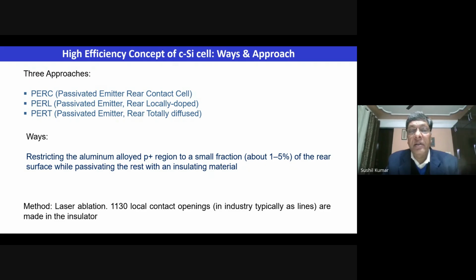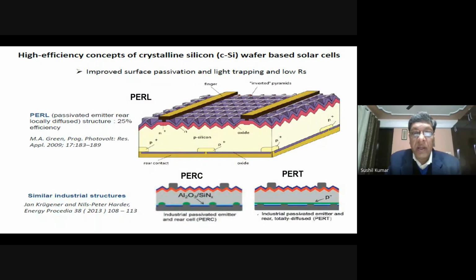What it was in 2014, 2015, about 17-18% industrial solar cell, and is gradually now moved to 23-24%. 22-23% is easily available now in commercial big size modules. So this happened because of this innovation in the rear contact. Other thing, this is basically how it is shown here. For the PERL, you have a local diffusion here, then you have a rear contact, and the oxide is grown here. In the PERC, this is how the grooves are formed, and even in the PERT, you have a P plus here. So there are some little differences.